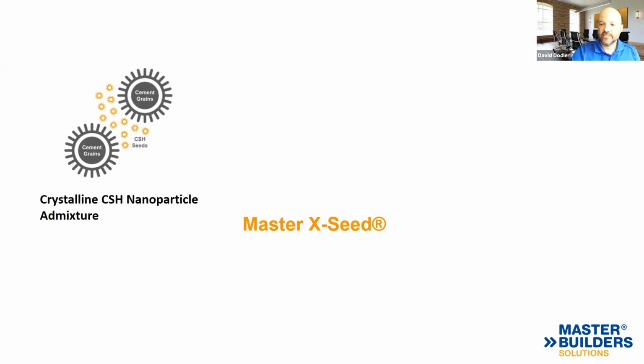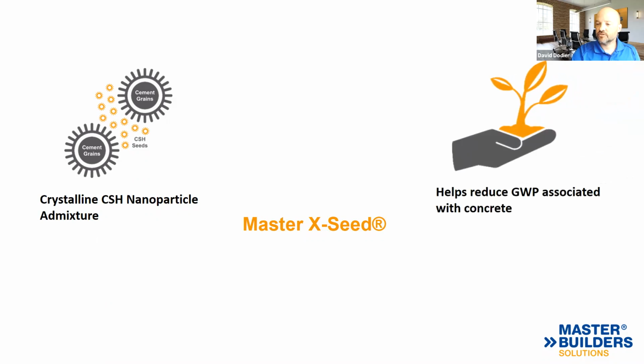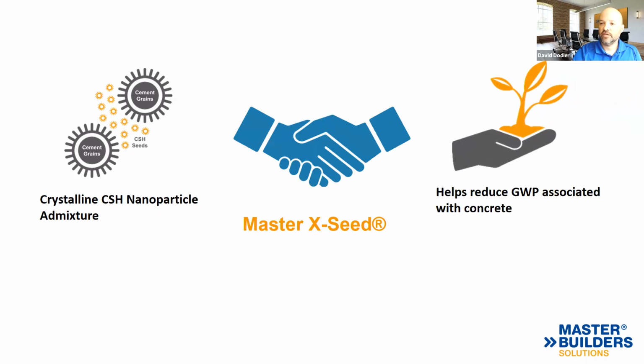What is Master X-Seed? Master X-Seed is a crystalline nanoparticle. It is a synthesized calcium silicate hydrate particle. It acts in a mechanical fashion versus some similar technologies that may act as a chemical reaction. So it acts through mechanical binding. Again, the Master X-Seed family helps reduce global warming potential on concrete, and they make a good pair.